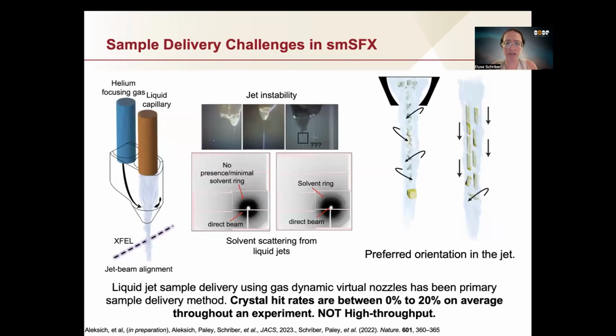One of the major challenges in small molecule SFX that we've found over the years is that sample delivery, this dynamic sample delivery with liquid jets, is extremely difficult. So the way that sample delivery works is you have a helium focusing gas and a liquid capillary, and the sample is delivered via the liquid capillary. The helium focusing gas is then delivered as well. And at the exit aperture, the gas acts as a focusing element to the jet. So as it comes out of the aperture, you get a nice conical jet by way of the helium focusing gas. And what this allows us to do is reduce our sample consumption and also reduce the amount of background scattering that you get from the solvent itself, which for biological molecules is very important.